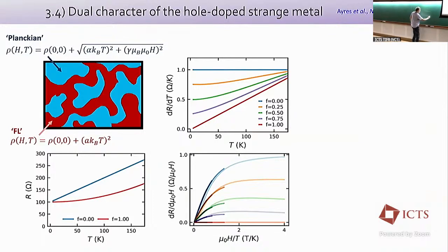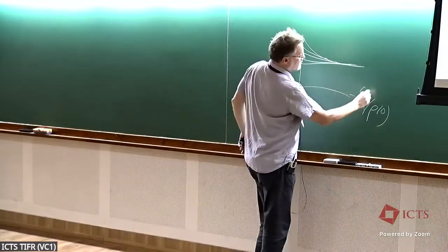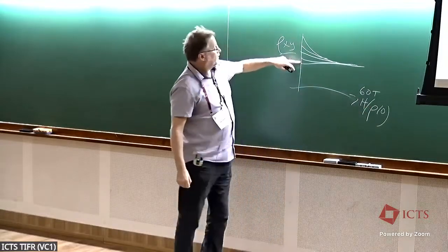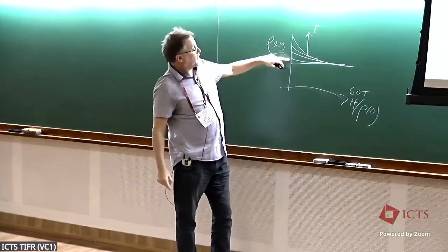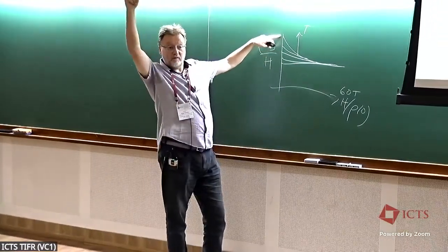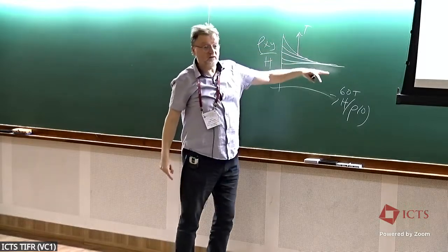And in fact, if you scale with the zero field resistivity at different temperatures, it does that. So this is going up to quite high fields, 60 Tesla or so. The zero field Hall coefficient is going up to about 150 Kelvin, then it comes down again. But in field, it starts to drop down.